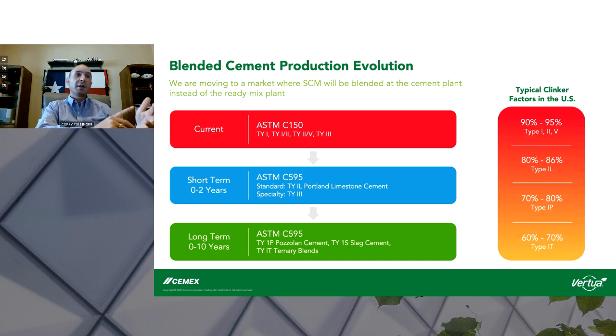We call that a Portland pozzolan cement, a slag cement, or a ternary blend. And the reason we're doing this is we're reducing what they call the clinker factor. And so what that means is when we produce clinker, it's a rock that forms when the cement raw materials, limestone and clay, go through the kiln. It comes out in a rock form. And then we put it in a mill and we grind it, just by adding in other things like natural pozzolans, things of that nature. We're reducing that clinker factor of what we're going to ship out. And so by doing so, we're also reducing the carbon footprint of that ton of cement.